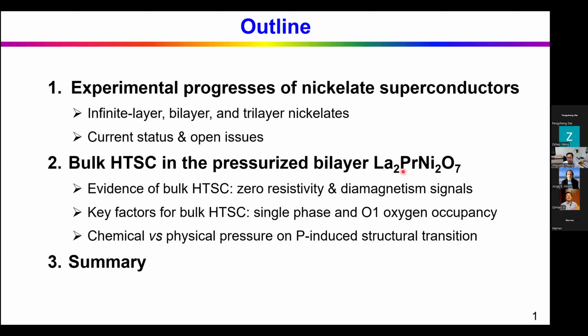In the second part of my talk, I will present our result that we confirmed the bulk high TC superconductivity by observing zero resistivity and diamagnetic signals. And I will try to show you there are two key factors for achieving bulk high TC superconductivity: you need to have a single phase, with no intergrowth between the 327 phase and other Ruddlesden-Popper phases, and there are negligible oxygen vacancies at the apical O1 site. And if I still have some time, I will discuss the chemical and physical pressure effects on the pressure-induced superconducting transition.